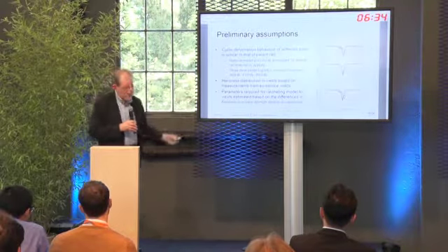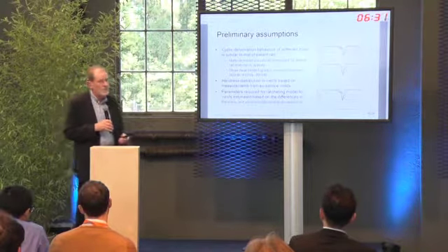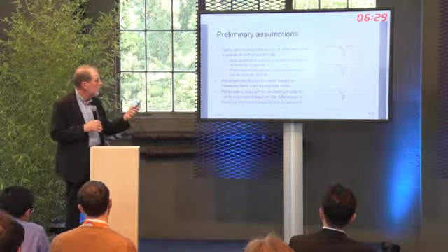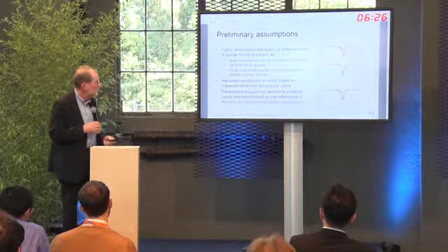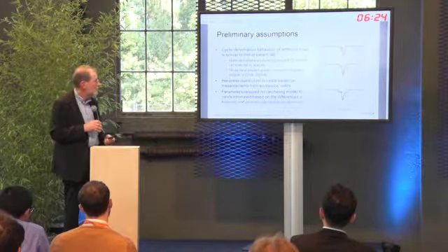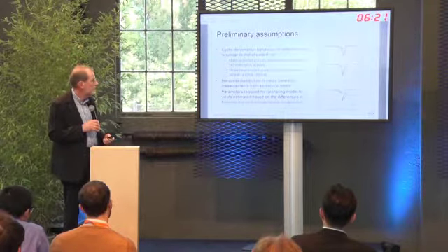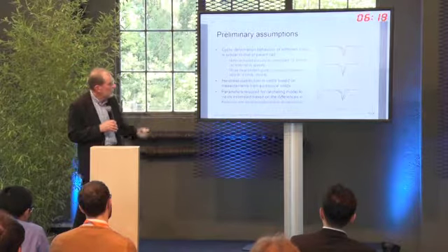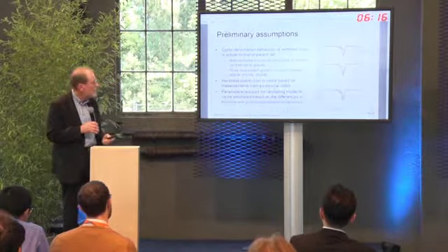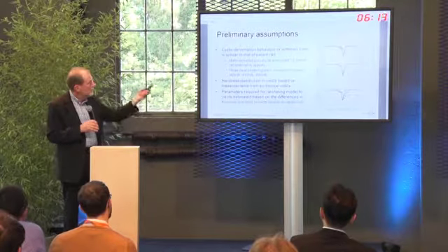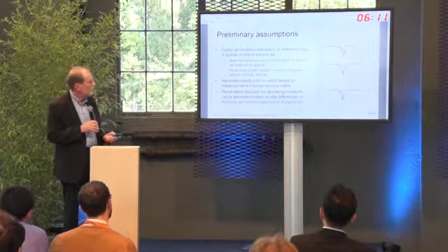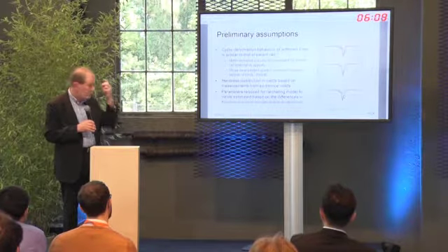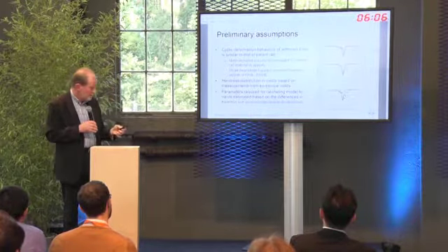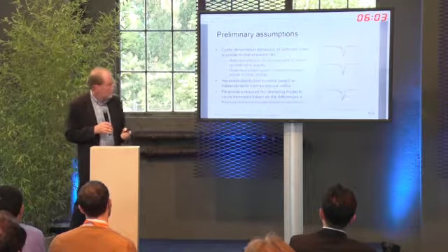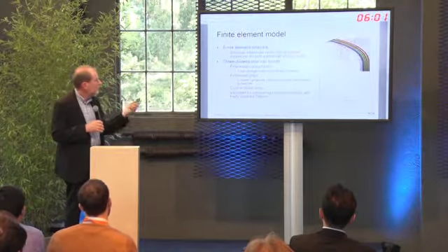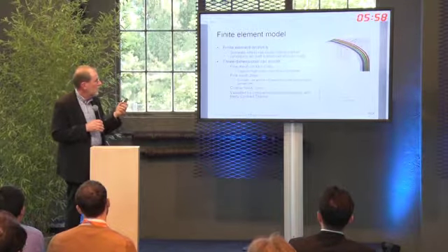We had ratcheting parameters for three heat-treated rail grades from the previous work, and so that was used to try and estimate some ratcheting behaviour for the material in the softened zone, based on the typical hardness distributions measured in welds that had come out of service. So this was the assumed hardness distribution in the flashbutt welds in the three different rail grades with variation in heat affected zone width.